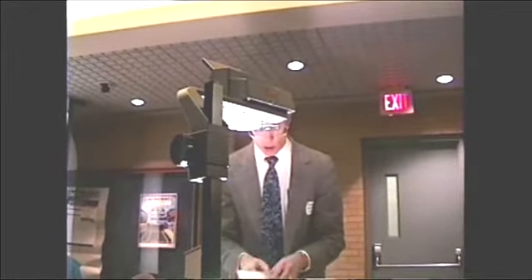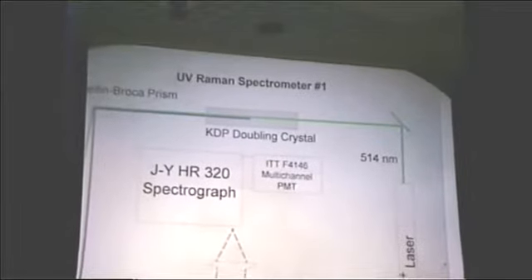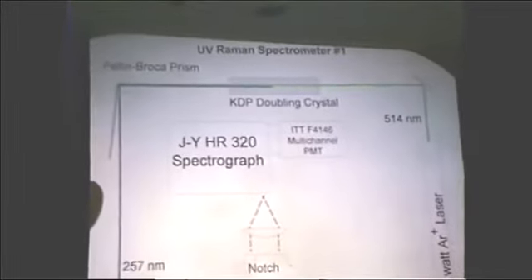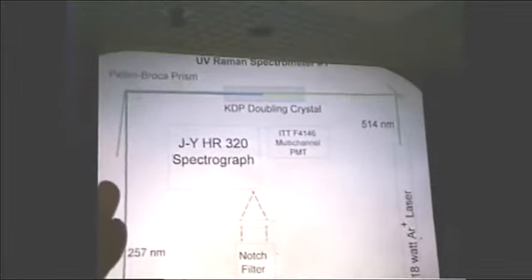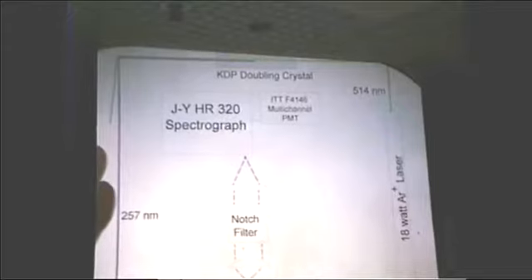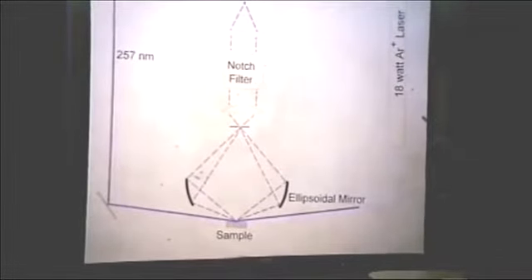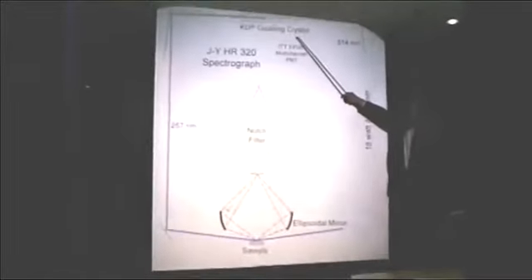Now, I found out about Asher's work about 3 or 4 years ago, something like that. And we had tried to do some Raman spectroscopy on single crystals with not too much success. But we had all of the equipment from that attempt that we had made to measure a Raman spectrum. In addition, we started another series of experiments where we had a very strong green argon ion laser that we were frequency doubling to produce ultraviolet light at 257 nanometers that we were using for photochemistry. So we weren't doing any Raman scattering with this, but we were using it to do photochemistry.